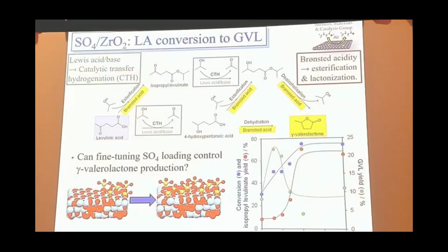If we vary the amount of sulfuric acid used to dope sulfated zirconia, you can see that the first thing that happens if you increase sulfuric acid content is the red lines increase, which is your isopropyl levulinate. So the catalyst, as you've got a very high concentration of sulfuric acid, you produce your sulfated zirconia. It's very good at esterification. At the low coverage end, where you've got a partial surface sulfation, you can actually start to see some green dots, which is your GVL.